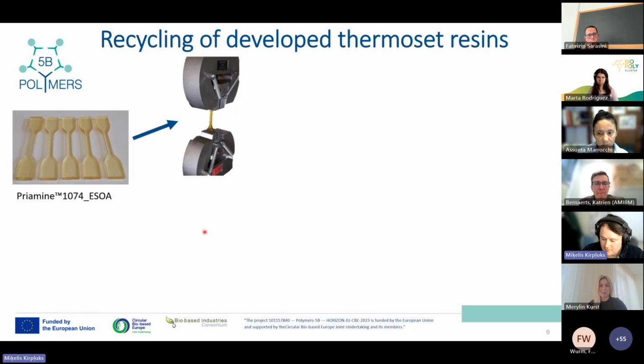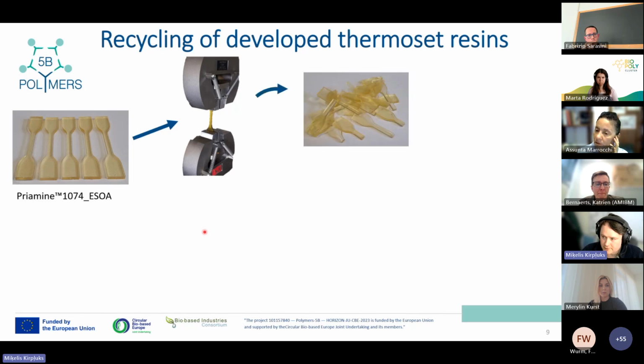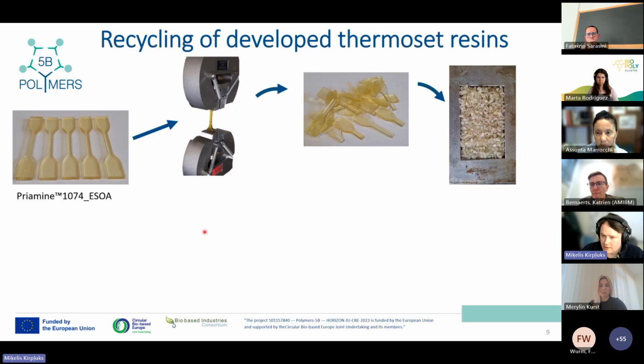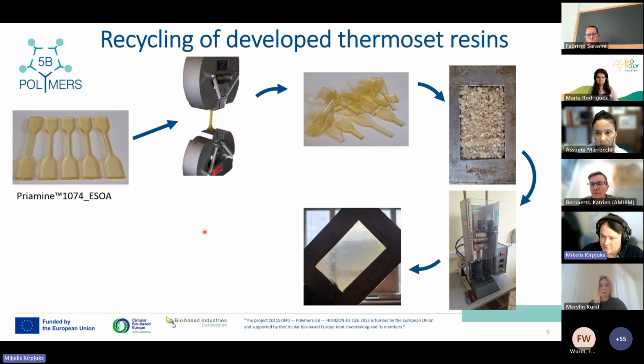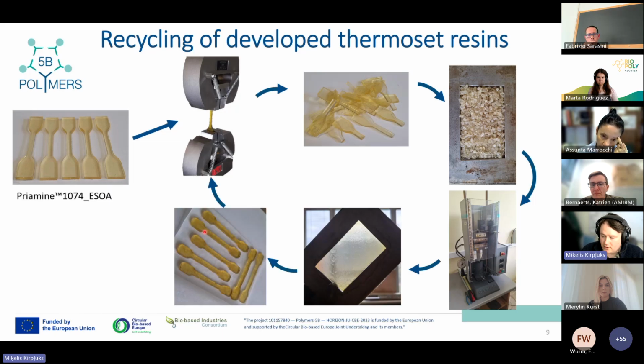special functional groups into the polymer network so that after the mechanical degradation of the polymer material, we can grind it and we can reprocess it as if it were thermoplastic. So aza-Michael thermoset resins have vitrimeric properties due to these beta-amino polyester groups in their chemical structure.